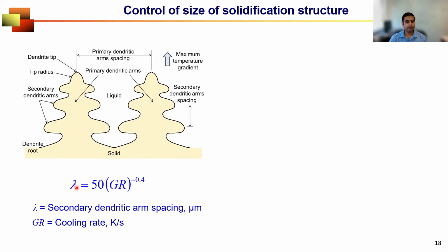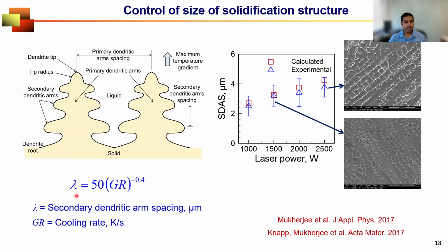Secondary dendritic arm spacing, which is this distance, is related to the cooling rate using this formula. Now 50 and 0.4 are alloy-specific constants. For steel, this is 50 and 0.4. If you are taking aluminum alloy or nickel alloy, they might be different. So once you have these and calculate the cooling rate from the temperature field, you can calculate secondary dendritic arm